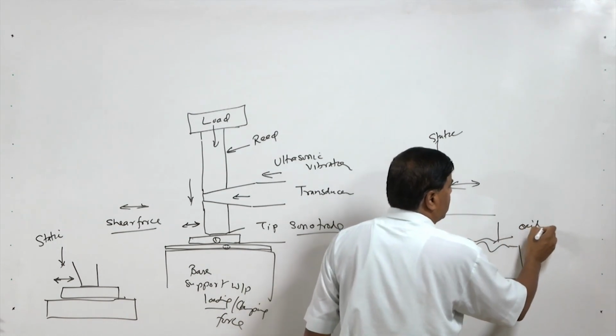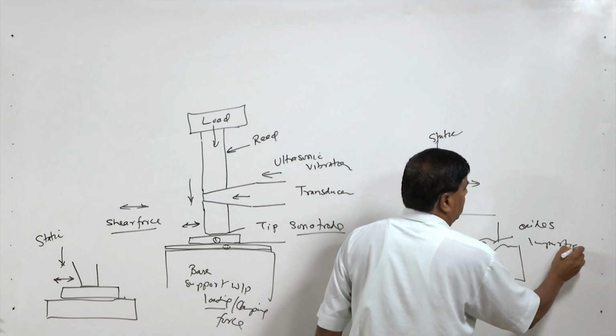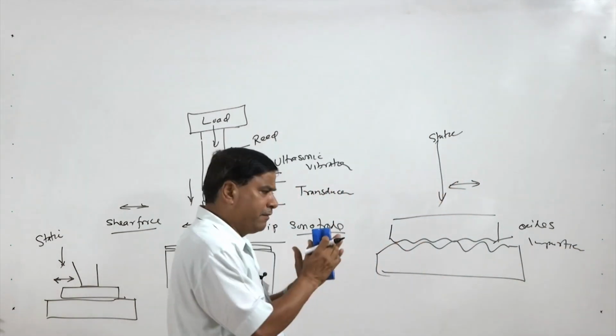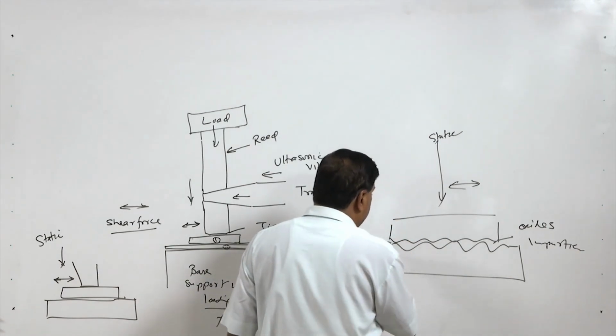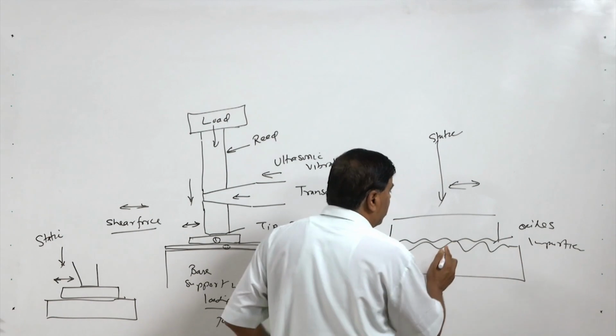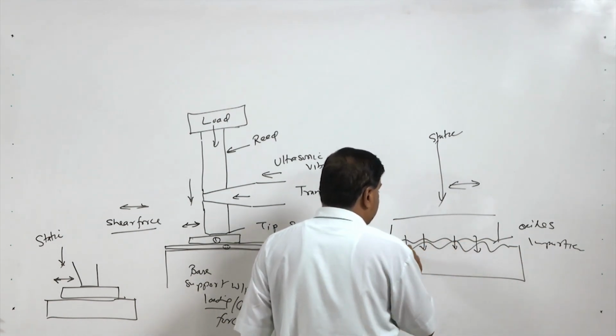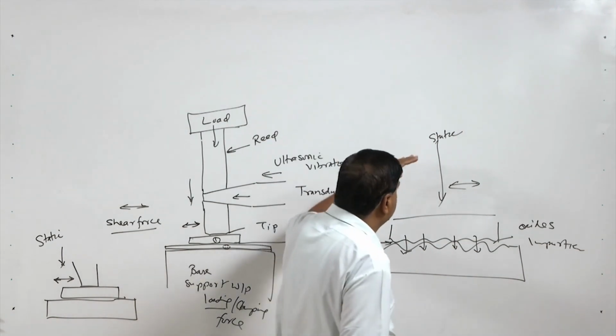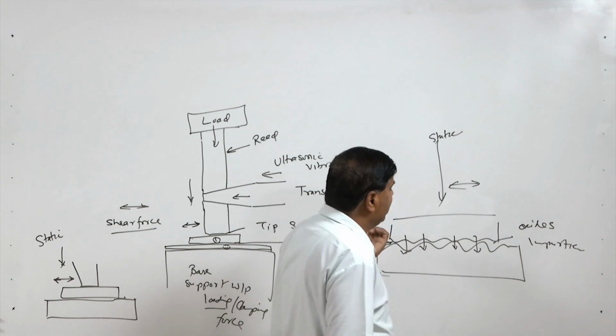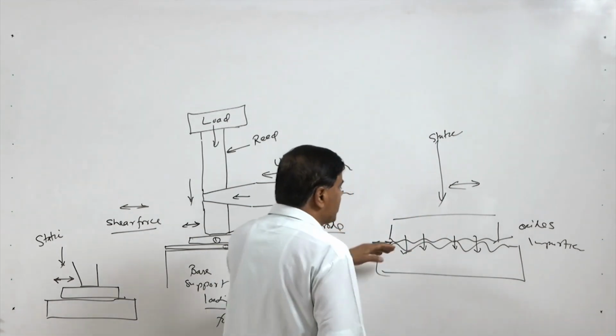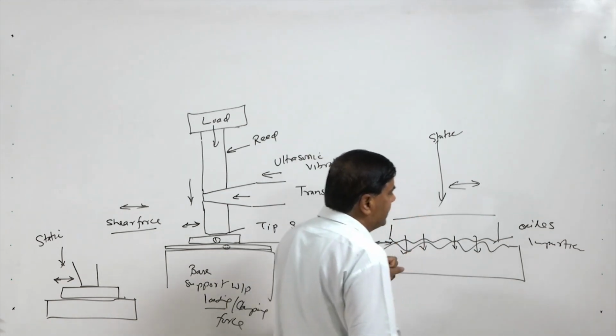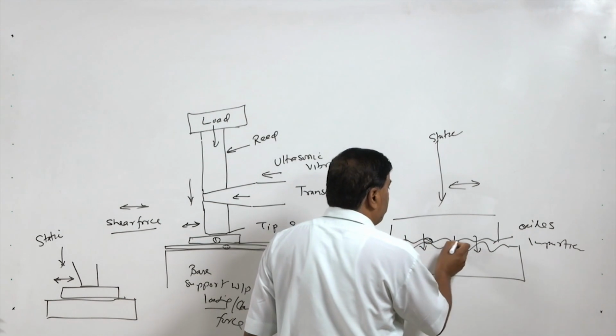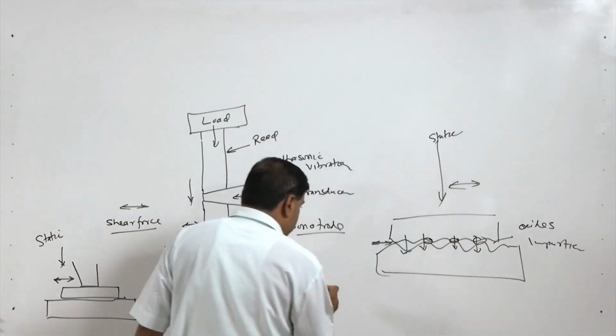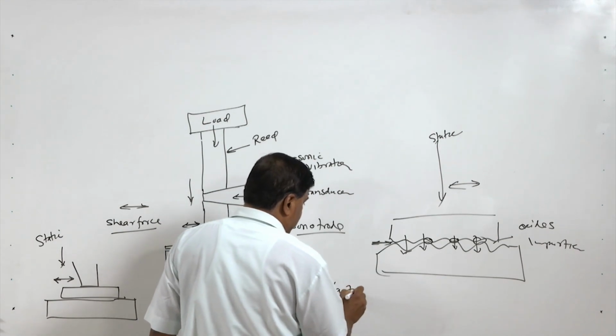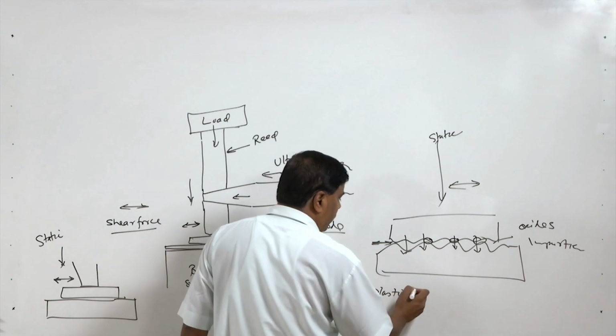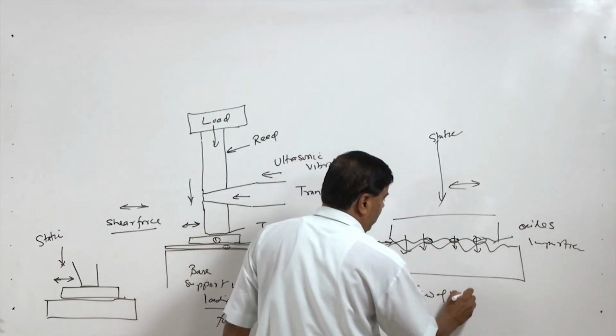initially the oxides and impurities are flushed out or removed from the interface. So, these impurities are removed and direct metal to metal contact is established in the initial stage under the effect of the static clamping force and the vibratory shear forces. Once this metal to metal contact is established, the actual contact area starts to grow, and this growth is facilitated by elastic plastic flow of the metal at the interface.